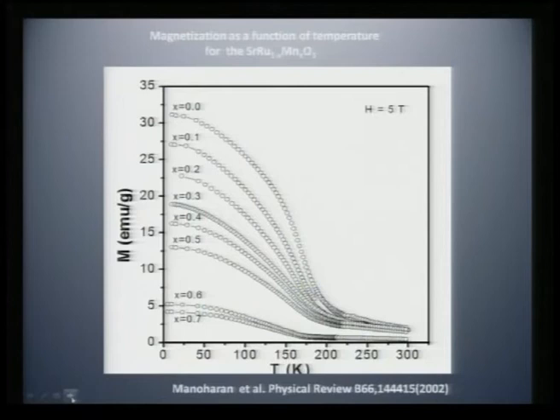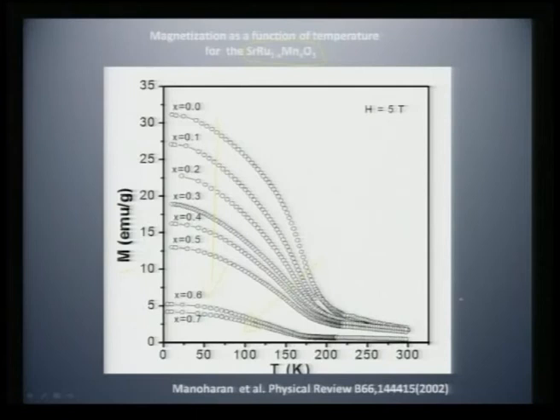So, this is a magnetization versus temperature curve for SrRuMnO3, where we systematically keep substituting manganese down the series. If you plot magnetization versus temperature, you can see there is a strong ferromagnetic loop, which is characteristic of these ruthenates. And as a function of this manganese substitution, the ferromagnetism keeps going down. Nevertheless, even at 70% of manganese, you still see a very strong, clear ferromagnetic exchange happening. So, why does it have to happen? Because the end member, that is SrMnO3, is an antiferromagnetic insulator, but something special should be happening as you substitute.